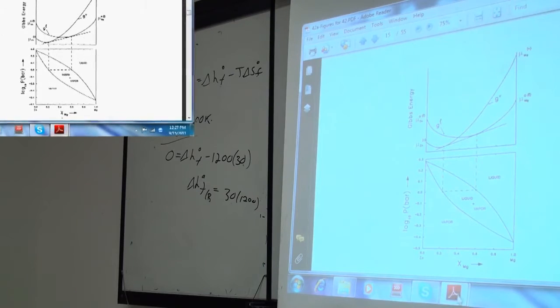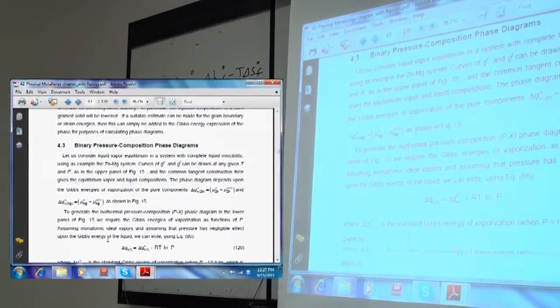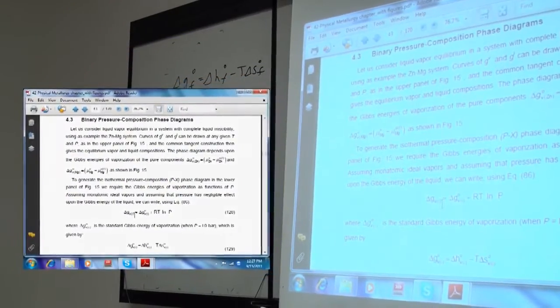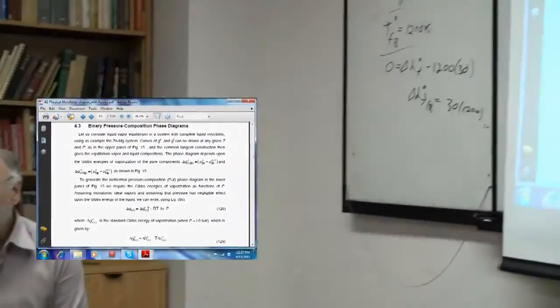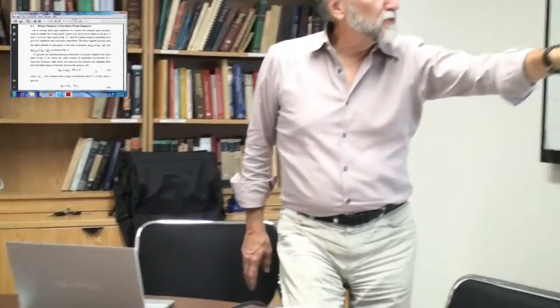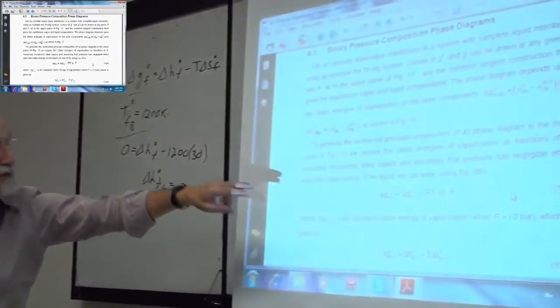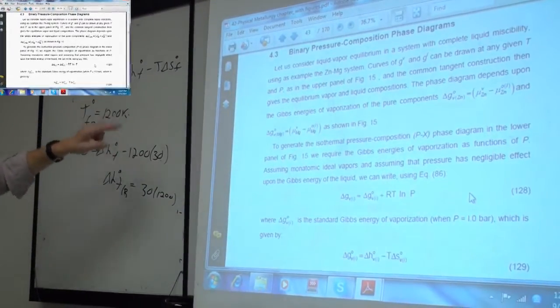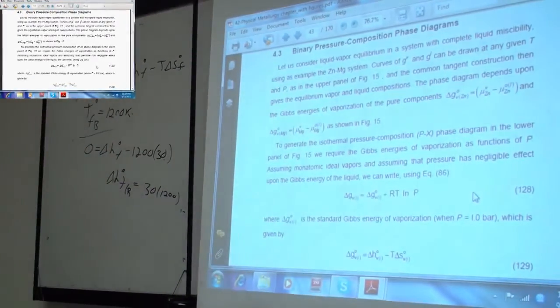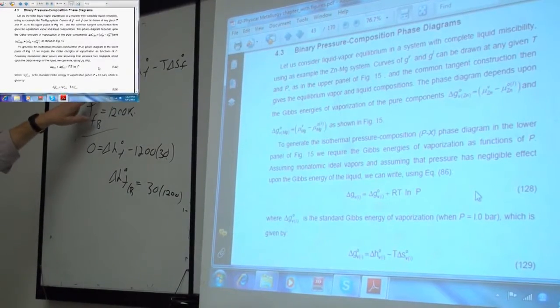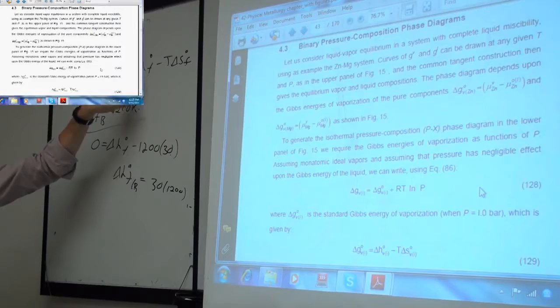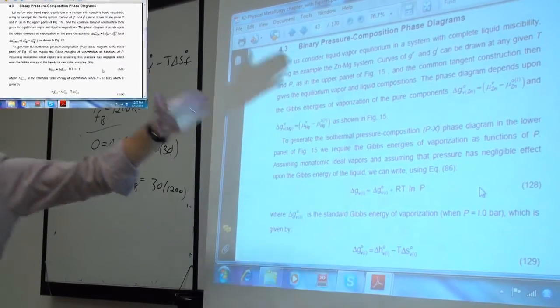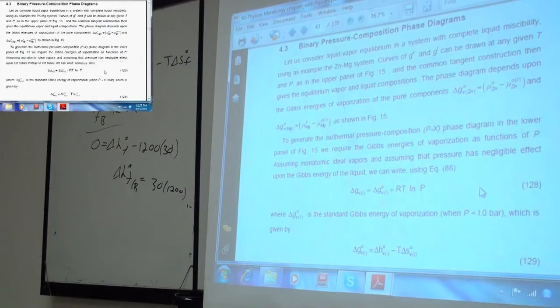And the expression we use is this one here. The Gibbs energy of vaporization is the standard Gibbs energy of vaporization, in other words, the Gibbs energy of vaporization going to a vapor at 1 atmosphere, plus RT log P. We've already derived that. Go back and think about it. But that equation there, 128, is sort of equivalent to this. This gives you the Gibbs energy of phase transition as a function of pressure when the temperature is constant. This gives you the Gibbs energy of phase transition as a function of temperature when the pressure is constant. So this equation here then allows you to change pressure and bring those two points together.